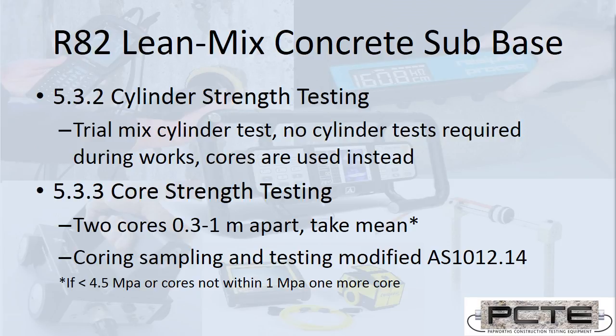The Roads and Maritime Services R82 lean mix concrete is a standard used for a cement road base, where they do not want to use cylinder strengths for testing. They don't want to cast a sample and break it, though they may use cylinder samples during trial mix testing. Instead, they are specifying that cores be taken from this road base. It defines that two cores should be taken and broken, and they should have a fairly even strength. If there's a difference of 1 MPa between the break of both samples, a third one should be taken. It also indicates that a third should be taken if the strengths measured are less than 4.5 MPa.